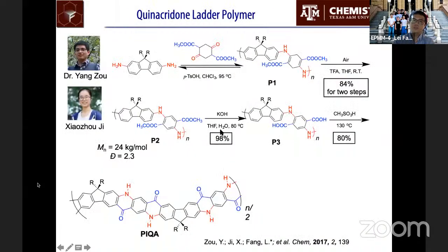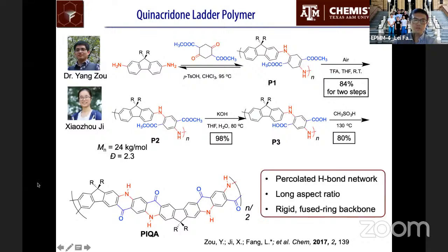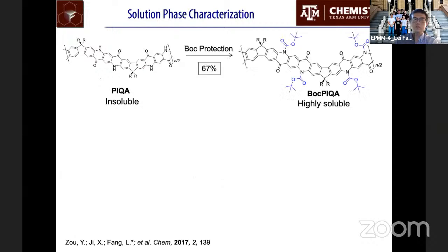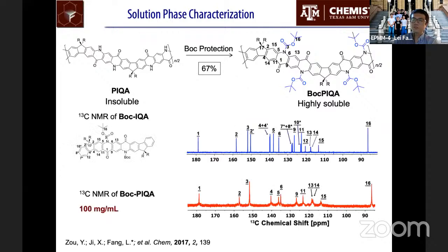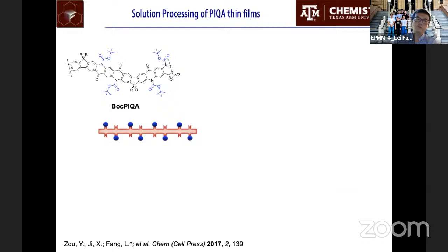We're also interested in synthesizing ladder polymers. I'm not going to go through the synthesis here, but we can make these fused ring macromolecules, which are unsurprisingly insoluble. But we could still solution process this by converting it into a soluble precursor through simple Boc protection. Now, this highly soluble material could be fully characterized and then used to cast thin films.